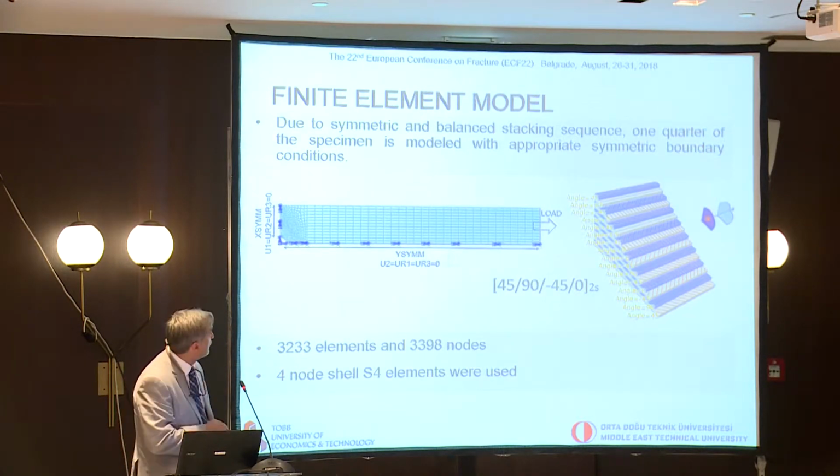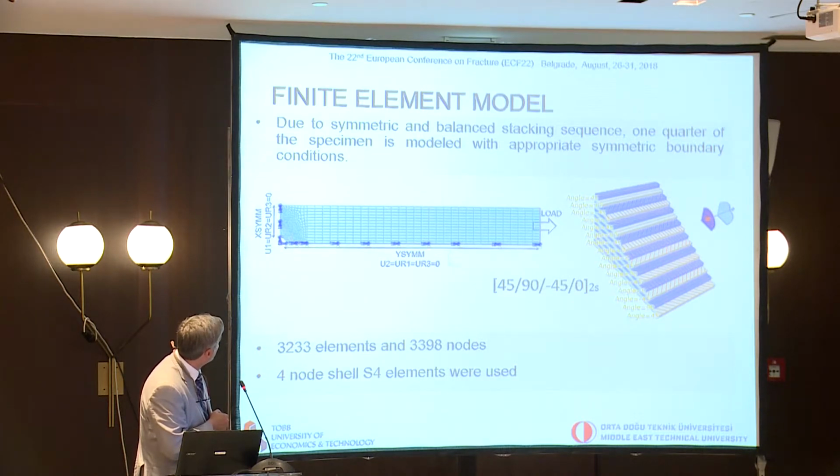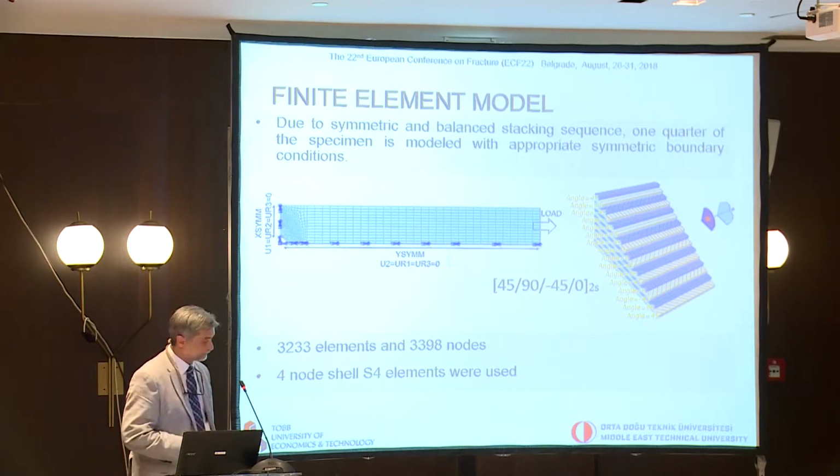We did a finite element model, very simple finite element model, where we used this symmetric and balanced stacking sequence and modeled 1/4 of the specimen with the hole with symmetric conditions on both sides and pulled it in this direction to determine the stress concentration with size for this layer.